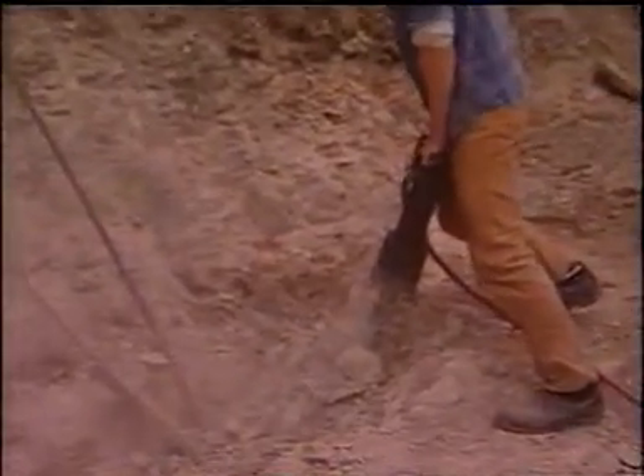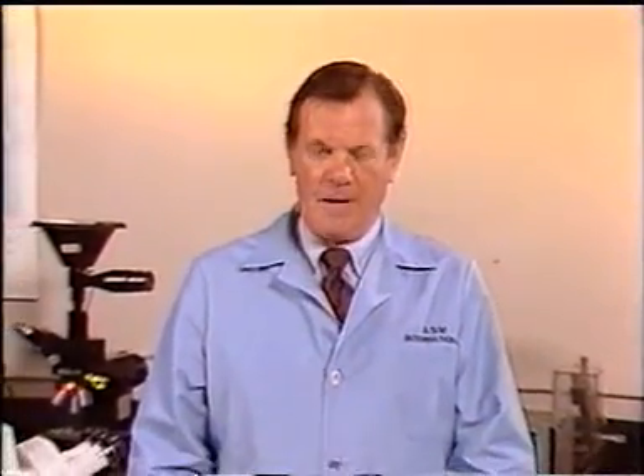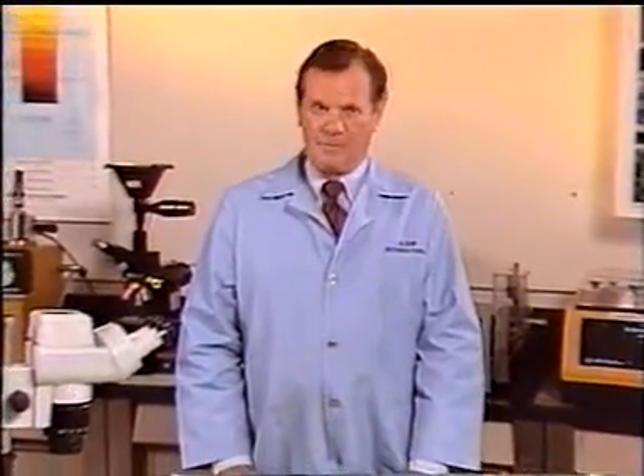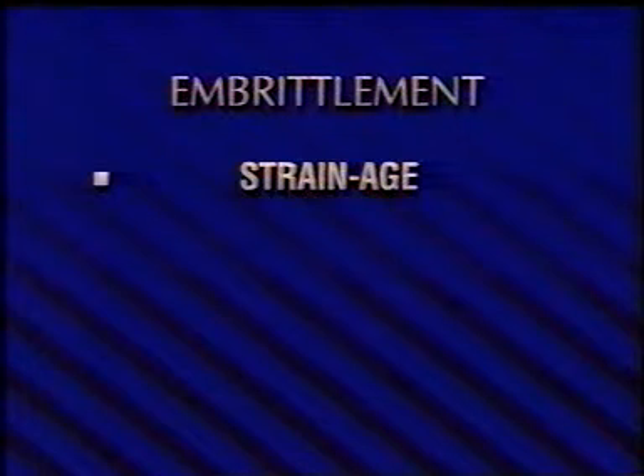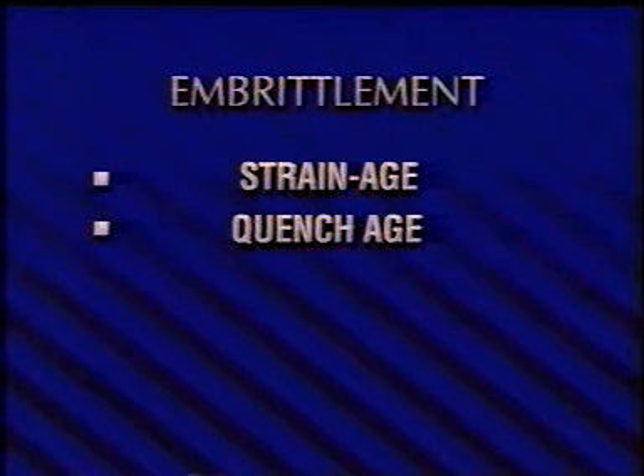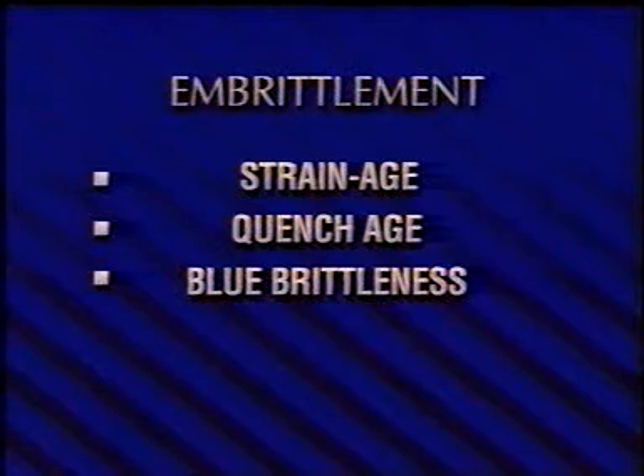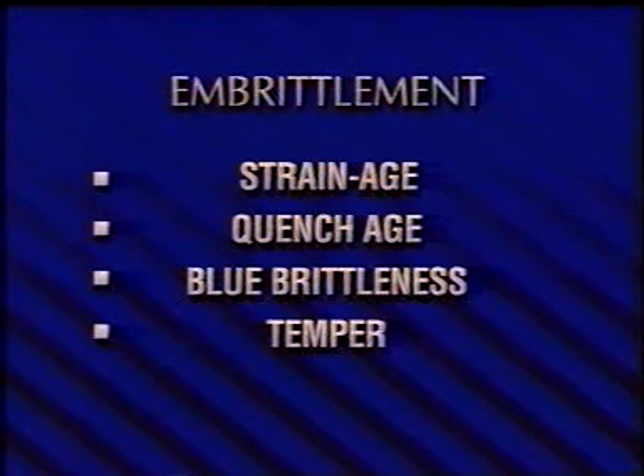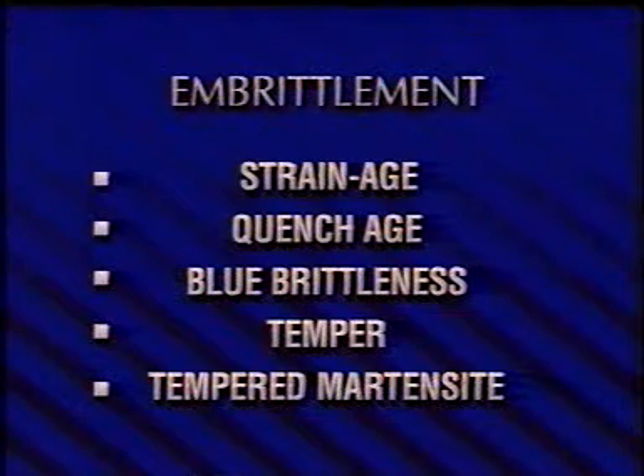Steel is not the only metal that encounters brittle fracture, but steel, a primary metal in many industries and products, is faced with a variety of potentially serious brittle fracture possibilities. Many forms of embrittlement of steel parts can lead to intergranular brittle fracture. At least 9 forms of embrittlement can occur during thermal treatment or elevated temperature service. Strain age embrittlement in low carbon steel. Quench age embrittlement in low carbon steel. Blue brittleness in some carbon and alloy steels. Temper embrittlement in constructional alloy steels. Tempered martensite embrittlement in high-strength, low-alloy steels. Stress relief embrittlement in weldments.